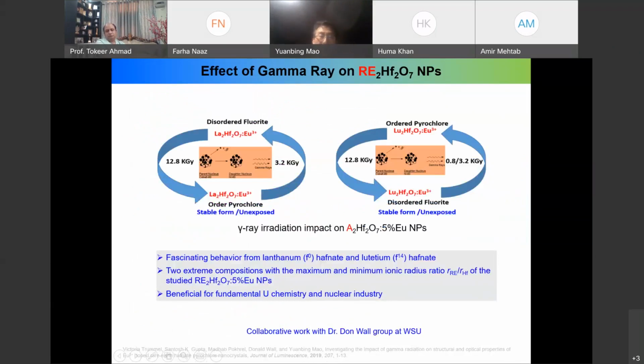So based on the results we had, lanthanum hafnate has this cycle. It starts with an ordered pyrochlore structure. After certain doses, it becomes a disordered fluorite, and then at a higher dose, it gets back to the original ordered pyrochlore structure. For lutetium, it has the opposite trend. So we've been wondering why there's this huge difference. We believe if we look at the atomic structure, lanthanum 3+ has 4f0, lutetium 3+ is 4f14, while the other four are in the middle, in between these two cases. So we believe that makes a difference.